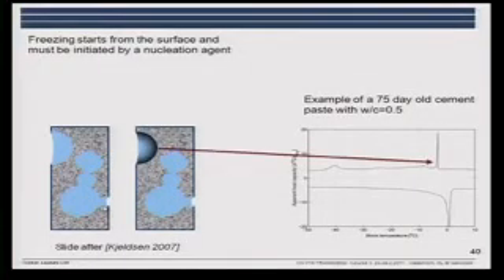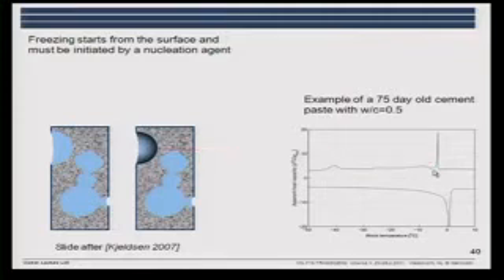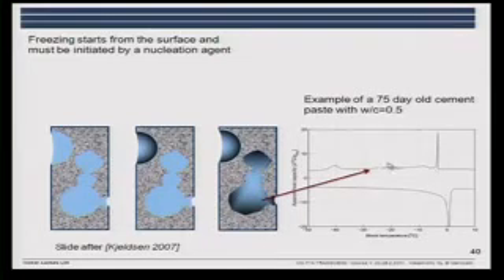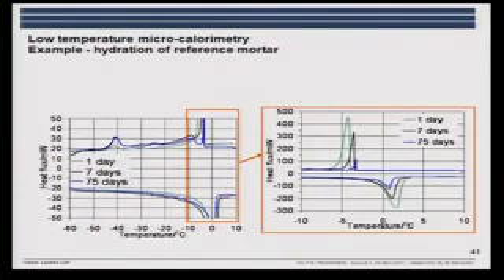And if we look at a sample here where we have pores, this is the water, and we have some freezing that takes place from the exterior, and we see the first peak. And at a lower temperature, the next part of the pore water will start to freeze, and finally the smallest pores are freezing. And then part of the pore water, which is not illustrated here, but if we have porosity here, it will not freeze at these temperatures.